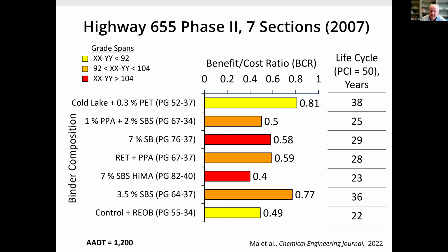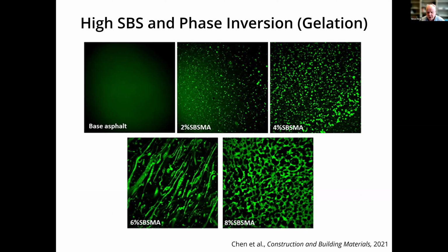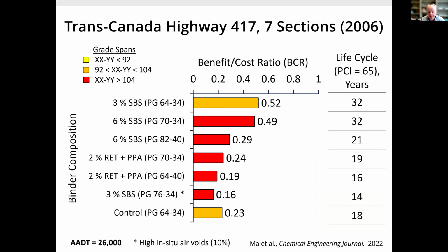I'm sad to say, Ontario, we still find motor oil in the asphalt cement supply today. It's banned in the OPS Muni 1101 spec, but agencies don't test, so they still get it today. The test on ash content is not sufficient. So what you get when you put in too much polymer, between 6 and 8%, it phase inverts. The polymer becomes the continuous phase, and the oil squeezes out slowly. This is the sweating and exudation process. It lets go of the aggregate, you get cracking.